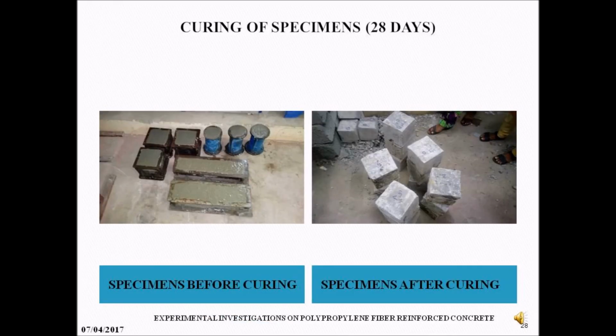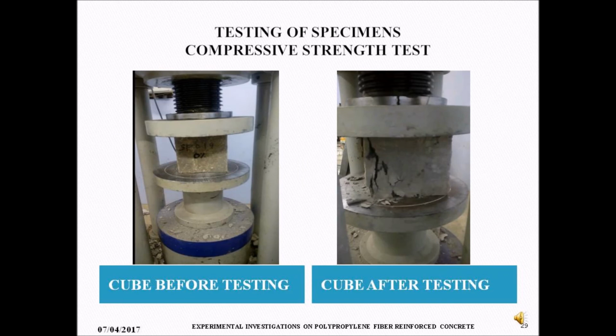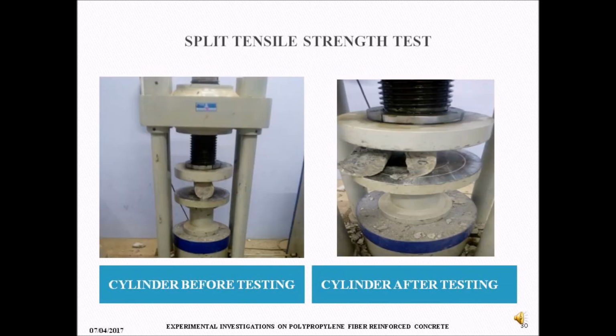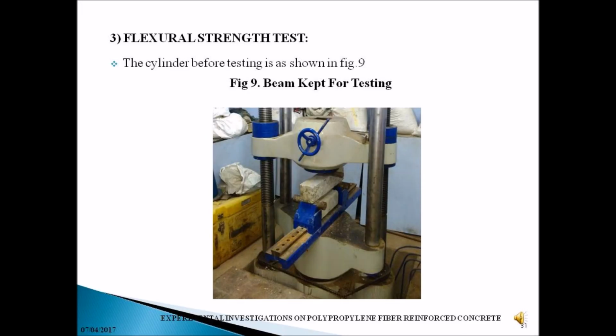Next, casting and curing of specimens. These are specimens before curing and after curing, that is after 28 days. Testing of specimens, compressive strength test. These pictures show before testing and after testing. Split tensile strength test, cylinder before testing and after testing. The specimen kept for flexural strength test.